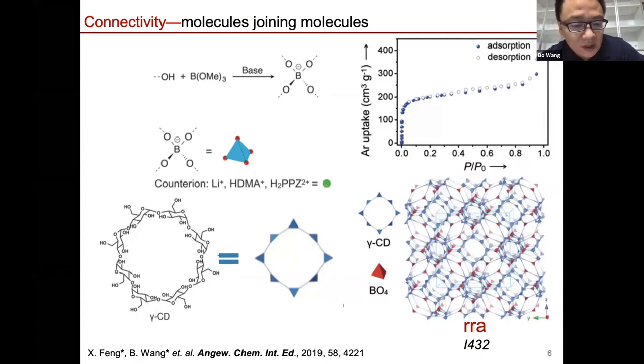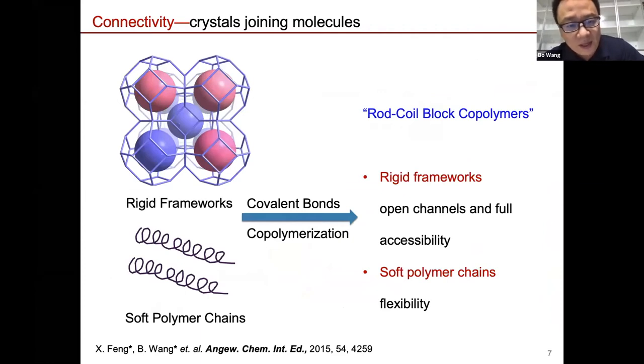If you use it to connect gamma-cyclodextrin, you get a highly crystalline structure, which is porous. And in this case, we don't have any other metals. Also, you can change different cations to balance the charge, so it can give you a rich chemistry regarding the guest-host interaction. But it's not enough, as we all know that a lot of COF and MOF structures, no matter how beautiful they are, are by themselves rather rigid frameworks. So when we look at those powders, those nanocrystalline materials, they are rigid and hard to process.